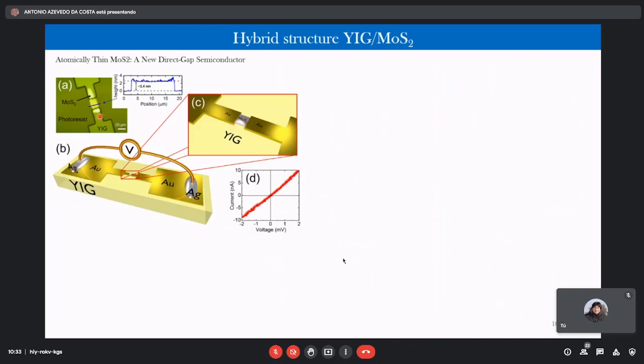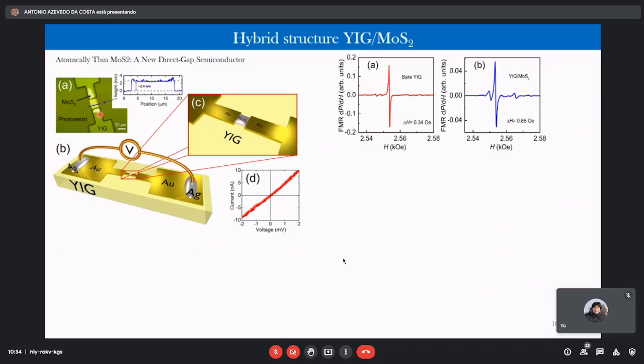And in this case, for instance, here I'm showing you the MoS2, which was transferred just by exfoliation to the surface of the YIG, and later we deposited contacts, gold electrodes, by lithographic process. And this is the ferromagnetic resonance of the YIG film, and after deposition of MoS2, the line width increased a little bit, so you can see the quality of this YIG is very nice, 0.34 oersted, the line width.